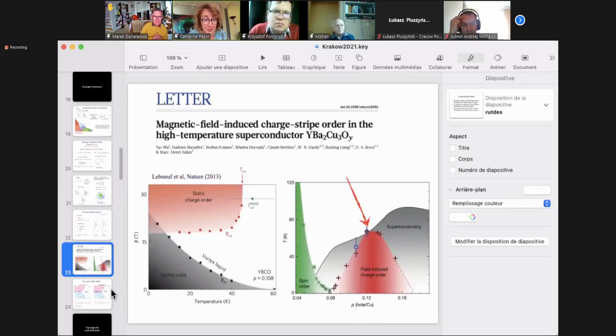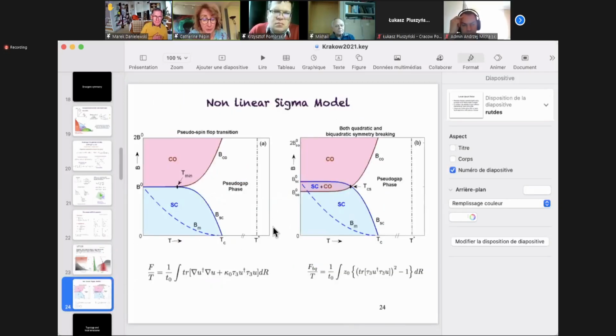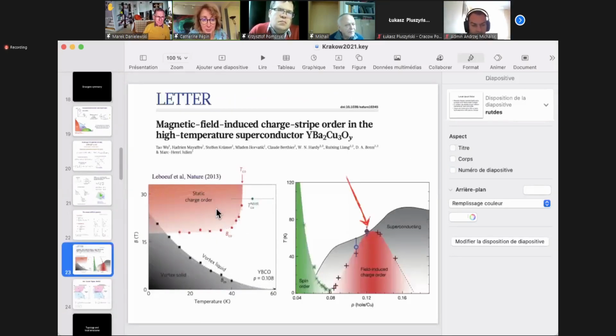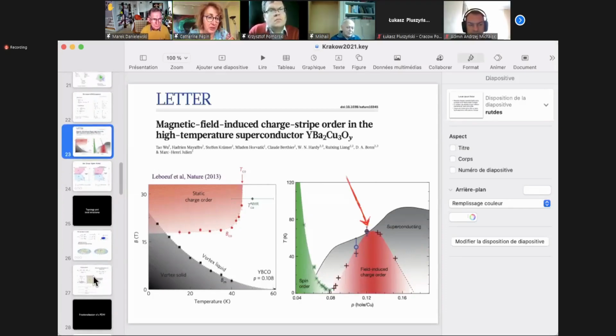Same idea, pseudo-spin. We tried to fit with Ginzburg-Landau, and we tried to fit with a nonlinear sigma model. With the nonlinear sigma model, you get the flatness for free. So it very much looks like you have a pseudo-spin, a kind of constraint relating these 2 orders, making a pseudo-spin out of the 2. With a pseudo-spin, you will get a skyrmion, that's a prediction.